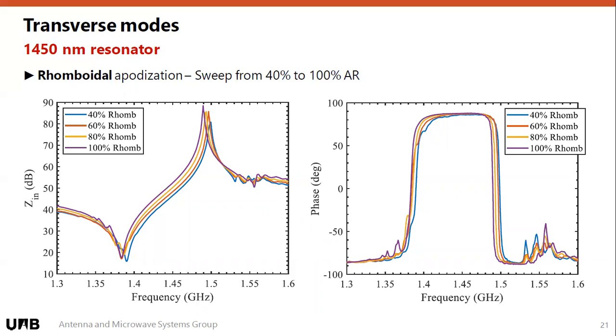And you can see, just by comparing it with the previous measurement, that you have no modes in between the two resonances. We cannot really see it now, but we will see that we have improved a lot in more electrical performance parameters. But we want to focus on this, and you can see that all resonators for any apodization ratio seem clean in terms of impedance, but we like to see it on the phase of the impedance. If you look at the phase of the input impedance of the resonator, you can actually see any mode that is sucking energy out of your main mode, because you're going to see phase going in opposite directions to the one you expect.